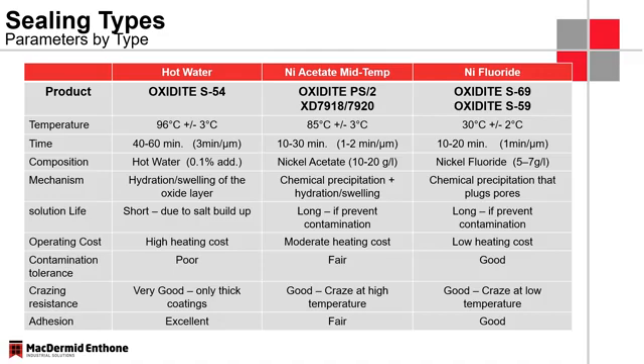And when we look at the temperatures here, I think we very quickly figure out why people like to use the nickel fluorides, the cold seal, at around 30 degrees. There are huge cost savings as opposed to using a hot water seal that works at around boiling temperatures. Some people actually use steam, even at higher temperature, to have better sealing properties and faster sealing times. And again, if we look at the sealing times here as well, we have huge advantages with the nickel fluoride cold seal, sealing in around 15 minutes for these parts.